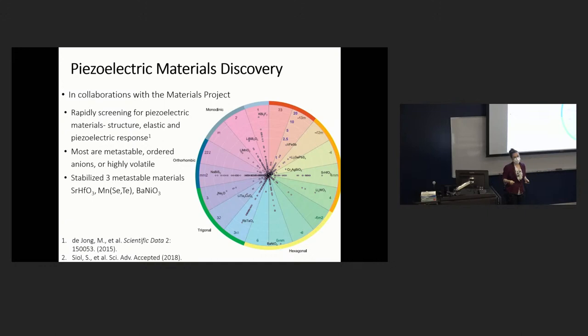Now, there's a reason why these things have not been done before, right? This was a list they came up with of new compounds, and that's because almost every one of these is either metastable or toxic or highly volatile, radioactive. You know, they're computationalists, right? But in this case, we went through this list and we found a couple that we could make. So we stabilized three compounds so far: strontium hafnate, manganese selenide, and barium nickelate. The first two we've shown are piezoelectric, and the last we're still working on. So here are some of the results for that.